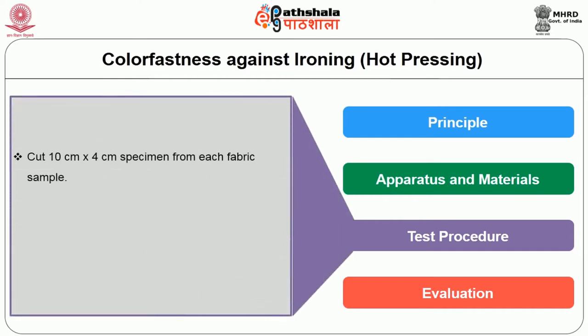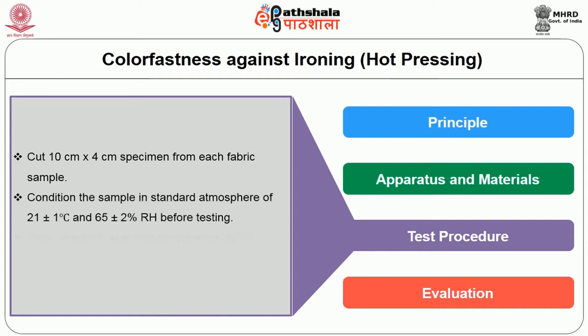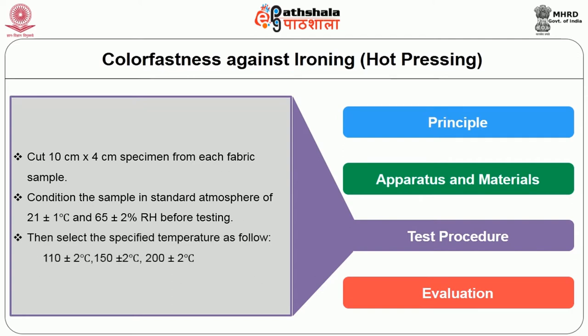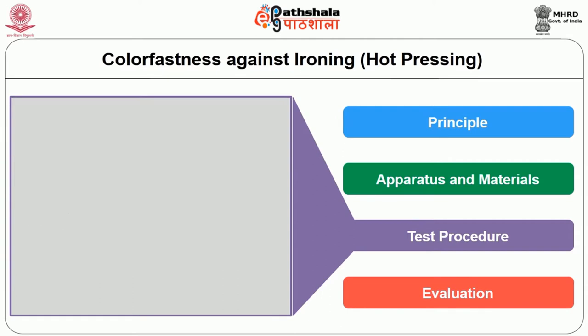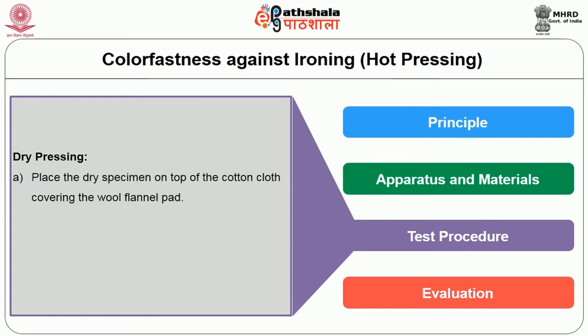Procedure used: a 10 cm by 4 cm sample is taken and conditioned before testing in a standard atmosphere of 21 plus or minus 1 degree Celsius with 65 plus or minus 2% RH. Then the specified temperature is followed for the testing in three ranges: 110 plus or minus 2 degrees Celsius, 150 plus or minus 2 degrees Celsius, and 200 plus or minus 2 degrees Celsius. Three types of pressing can be evaluated. The first one is dry pressing. Place the dry specimen on top of the cotton cloth covering the wool flannel pad.